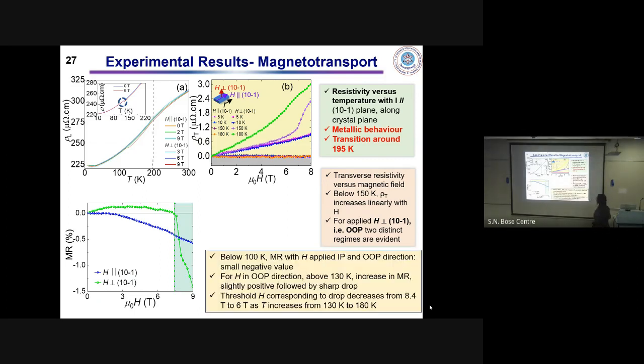And not only that, in order to study this, we have also performed magnetoresistance measurements, the longitudinal magnetoresistance. I have not shown all the curves here, but what we have observed is that below 100 Kelvin, the magnetoresistance with the magnetic field applied in both directions shows similar behavior. It gives a small negative value and it doesn't show any sharp change.